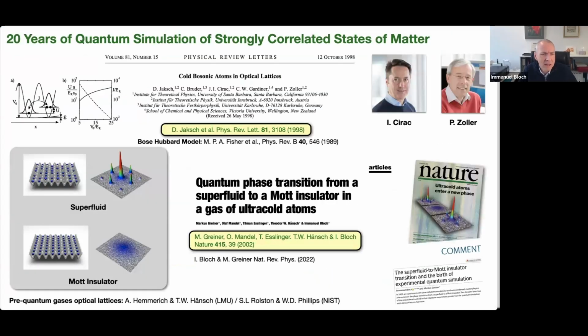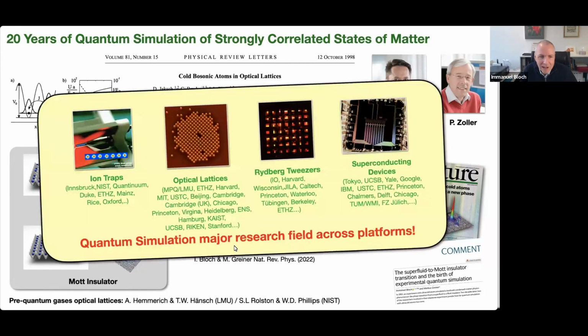Now, for me, my path into this world of quantum simulation started, as Michal was saying, with this phase transition from a superfluid to a Mott insulator, taking this weakly interacting Bose-Einstein condensate and making a very strongly interacting gas of particles by putting these atoms into an optical lattice, making the kinetic energy of the particles very small, and thereby having the interactions between the particles dominate. That basically induced this phase transition to a Mott insulator, and basically goes back to pioneering ideas of Ignacio and Peter, who outlined this. So that's already quite a while back, and the field has moved quite a bit.